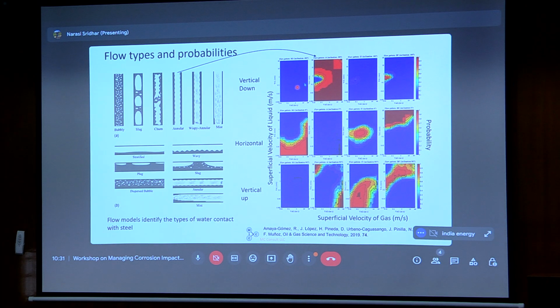So here, the probability is just plotted as color codes of various flow regimes plotted in terms of superficial velocity of gas, that is equivalent velocity as if the gas is completely occupying the pipeline, compared to the superficial velocity of liquid, which is the equivalent velocity of liquid if it occupies the total cross-section of the pipeline. Of course, in a gas-liquid mixture, there is a proportion of these two, so they occupy a partial cross-section of the pipeline. And you can see that annular flow becomes predominant when the pipeline is facing vertically down. When the pipeline is facing vertically up, there are some regions where annular flow becomes important. So flow model has many uncertainties, and we have to capture these uncertainties. Corrosion models also have uncertainties, and we have to find a way to capture them.